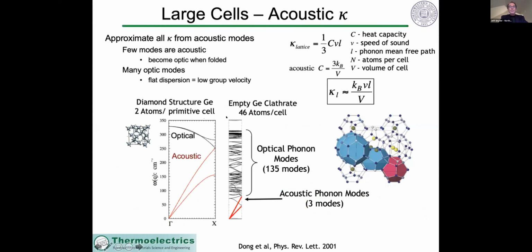So a simple explanation for how the lattice thermal conductivity can be inversely proportional to the volume of the unit cell is simply by taking a first order approximation that the heat is carried by acoustic phonons, which travel like waves, as opposed to the optical phonons, which we'll talk a little bit more about later. But one explanation would simply be that the velocity of these phonons, proportional to the slope of the dispersion relation, is clearly quite high for the acoustic modes and much lower for the optical modes. And so as we get to a large unit cell, we see that there's only 3 acoustic modes per large unit cell, but there are many optical modes, and many of them have become very flat, and that reduces their velocity, and so they transport heat much slower. And so by approximating them as not transporting heat at all, we can explain a volume dependence for the thermal conductivity.